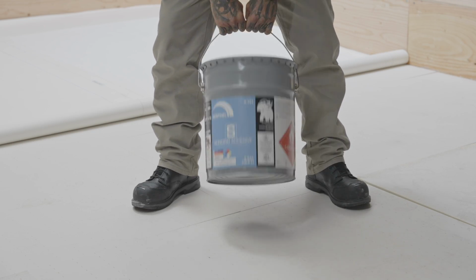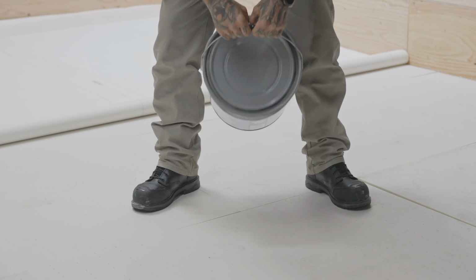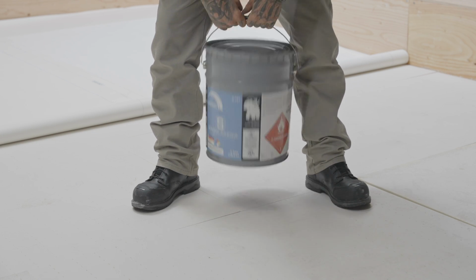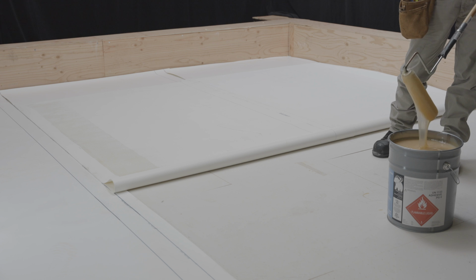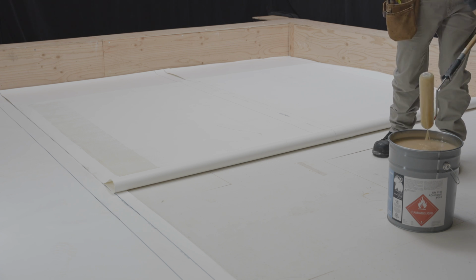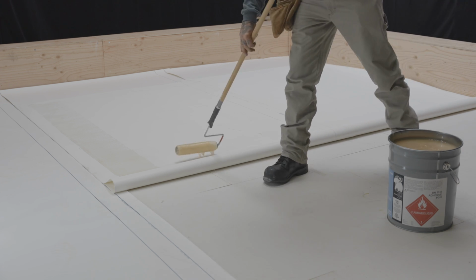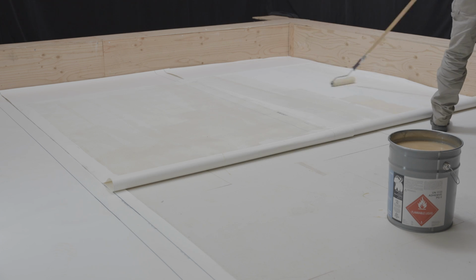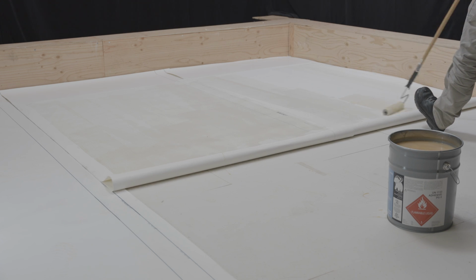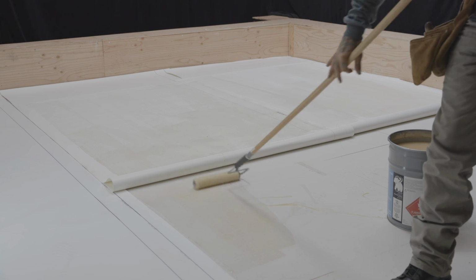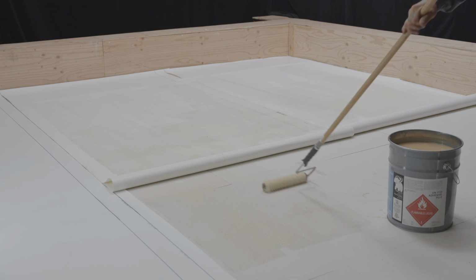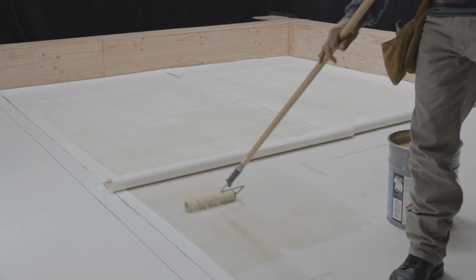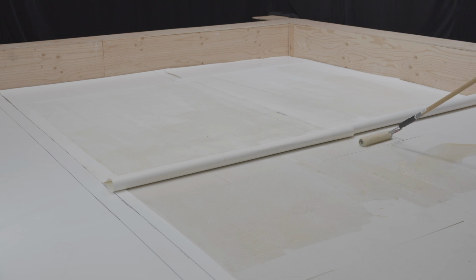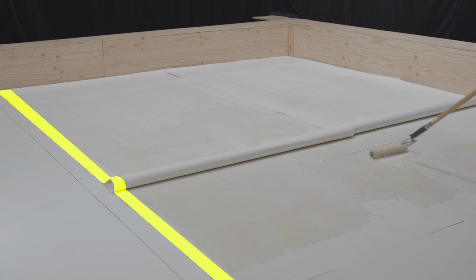Beforehand, hand mix thoroughly the contents of the pail until a homogeneous mixture is obtained. Do not pour the adhesive directly onto the substrate. Instead, use a solvent-resistant roller with a minimum of 3/8 of an inch. Apply the adhesive to the back of the bare PVC membrane and to the field surface substrate. Refer to the coverage rate indicated on the technical data sheet to know the quantity to apply. Be careful not to apply adhesive to the overlaps, as they will be hot air welded.